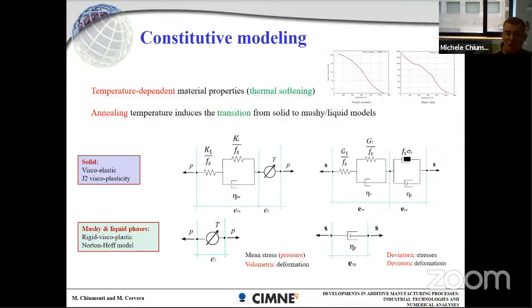So now, the transition between solid and mushy behavior. Typically, in my publication, I was putting the solid fraction as a transformation parameter able to switch from one to the other. But we noticed in the last year that the key parameter to move from solid to liquid behavior is the annealing temperature. So just to have an idea, the liquidus temperature of titanium is about 1,600 degrees, while the annealing temperature for the transformation of the constitutive equation goes at 900 degrees, so almost half of the temperature. So this means that we are considering a viscoelastic, viscoplastic model till the annealing temperature, and then we move to this viscous model.